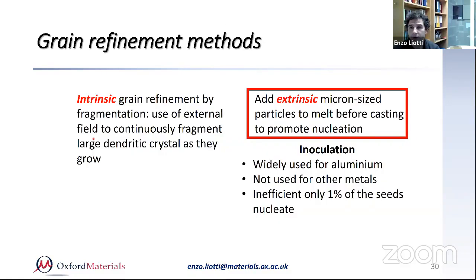Of the TiB2 particles you put in an aluminum alloy, probably only 1% of the seeds nucleate. The rest is inactive. So it also doesn't work for intermetallic phases. There is not yet a grain refiner for the intermetallics in aluminum alloys, for example, in the 2000 or 7000 series.